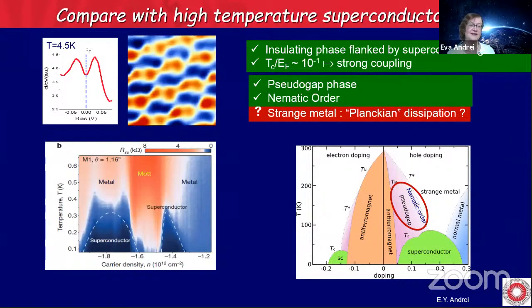So let me summarize here. What we have seen is that when you bring the Fermi energy within the flat band, you get a pseudogap phase. This is called the pseudogap. This is very similar to what is seen in the high temperature superconductors. And we get a nematic charge phase of charge stripes, which is very much like what one sees in the high temperature superconductors. Strange metal behavior has been seen in our transport measurements, as well as in other groups' transport measurements. So it looks like we can actually check all these questions here.